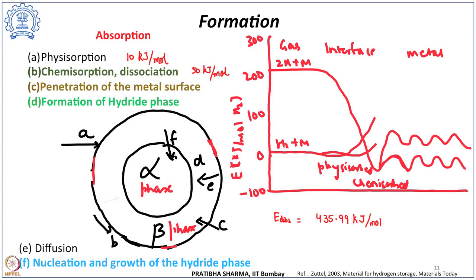Now, there is an activation barrier between the hydrogen molecule and its dissociation into hydrogen atoms. Also, there is a barrier towards hydrogen being chemisorbed onto the surface of the metal. So, chemisorption of the hydrogen. Now, these potential energy, activation energy barriers need to be overcome, and then the process occurs. So, that requires sufficient energy to be supplied for overcoming this activation energy barrier.